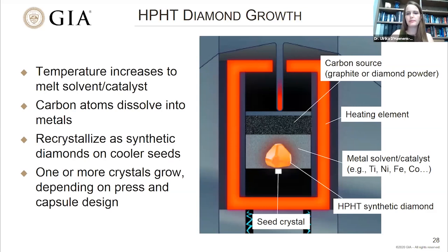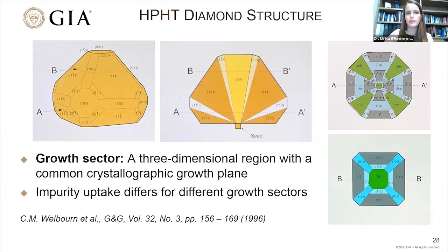And what you can see here is your little small seed crystal, and on top of that, this sort of large crystal that has grown out of it, this orange crystal. And that's the HPHT diamond. So that's the new diamond material that was synthesized. And the structure that that diamond has is known as a cube octahedral shape. So an octahedron, again, is this square-shaped pyramid, two pyramids stuck to each other. So you have this sort of pyramid shape, and then you just sort of shave off the corners, which is the cubic shape to it. So this is the cube octahedral structure.